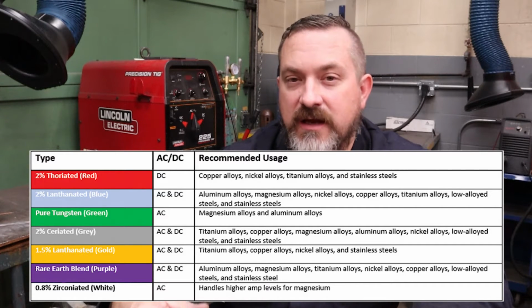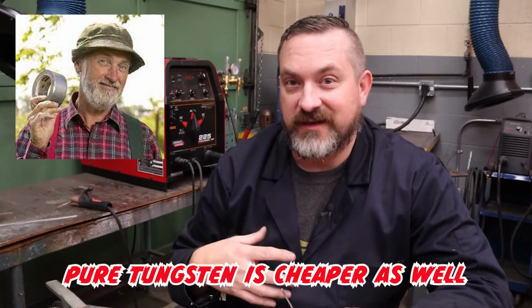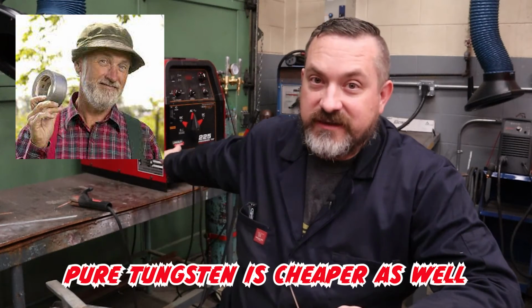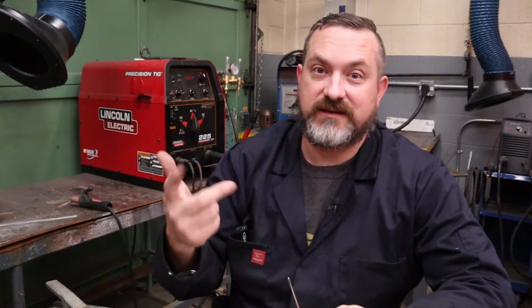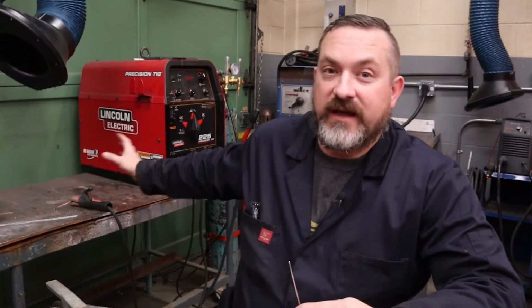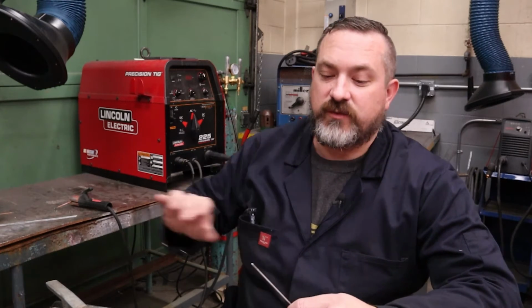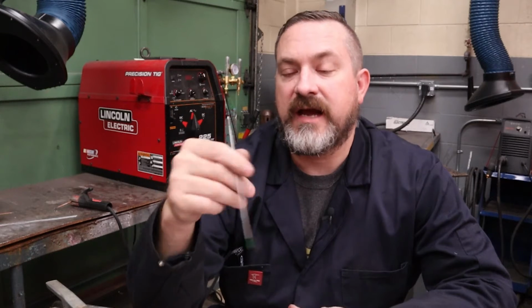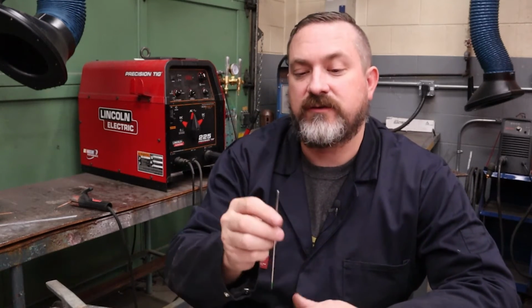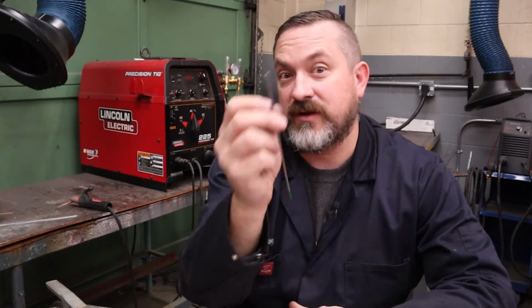Now, in our shop, we are very much a Canadian shop, so we stick to the red-green. So red is 2% thoriated. We use that when we're on DC negative for all our steel, stainless, cast. And then when we get to AC and we flip that switch, we switch up to our green, which is the 100% pure tungsten. Now, because I like to run mine on the cleaning cycle a little bit too hot, I do start with a little ball on the end of my tungsten. So let me show you how I do that.